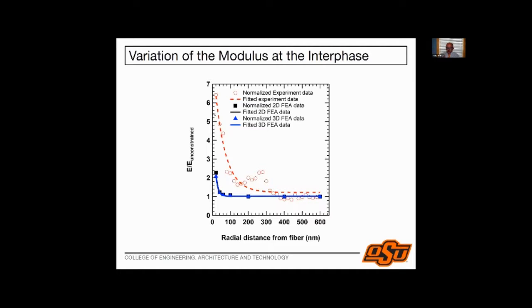This means that the epoxy, the way these composites are made is that you have the fiber, and then you put the epoxy and you cure the epoxy. The only reason why this is higher is because the curing characteristics of the epoxy right next to the fiber are different. And now that has changed. The cross-link densities are probably higher because of the presence of the surface, and that's why the modulus has gone up. So this modulus will then end up affecting the load transfer mechanisms.